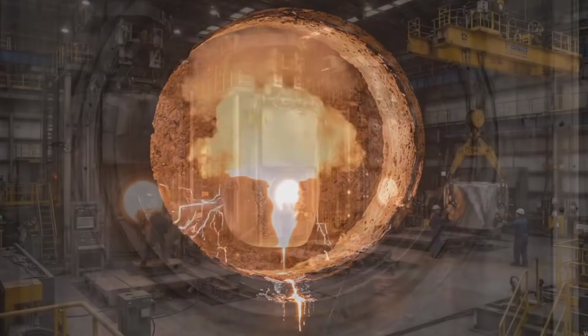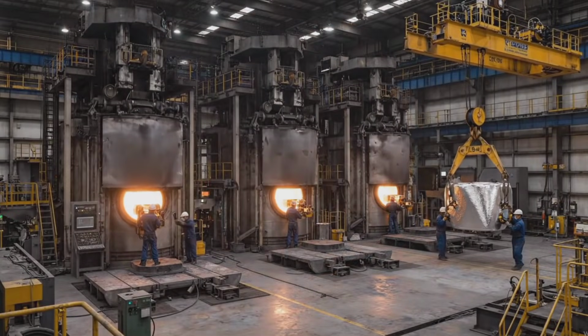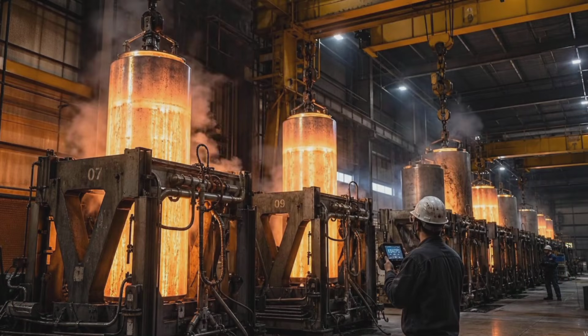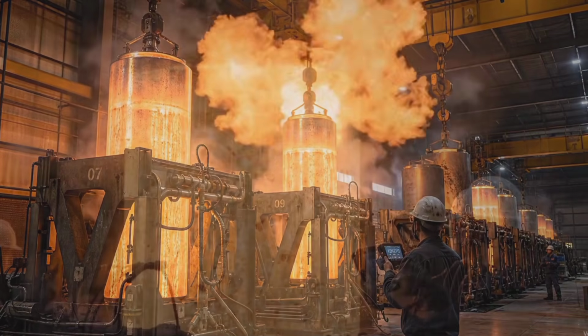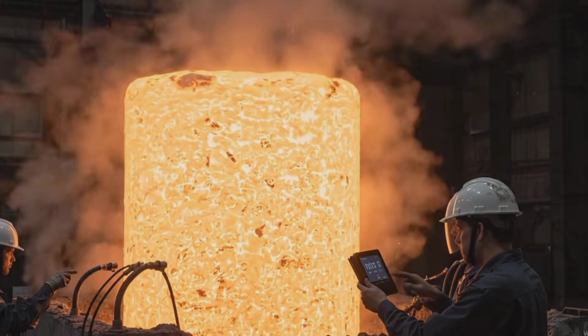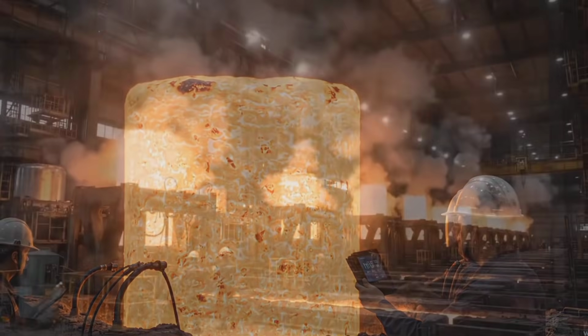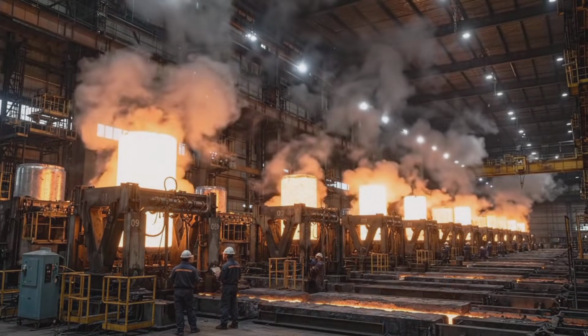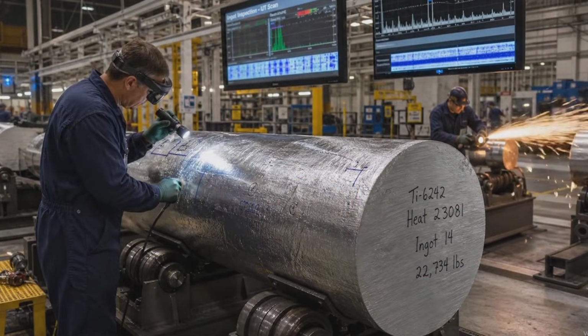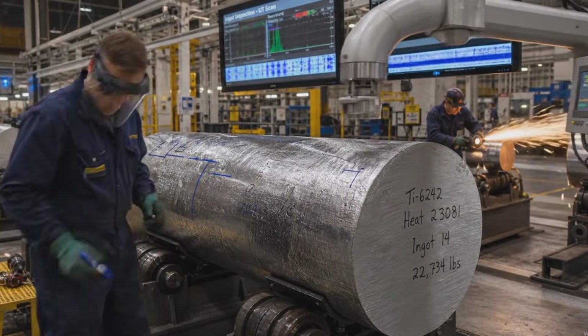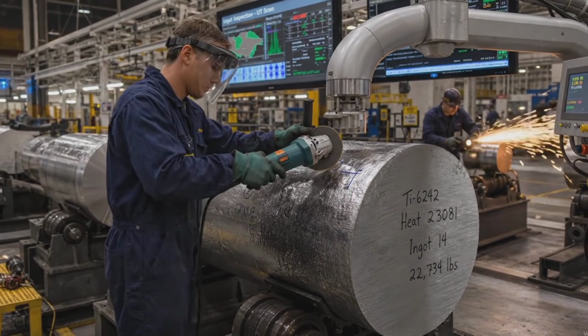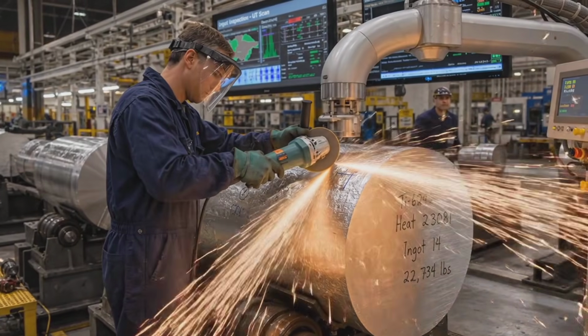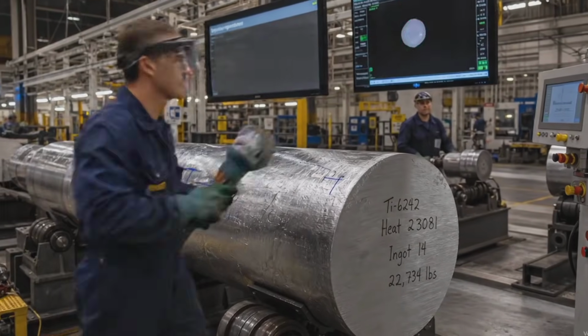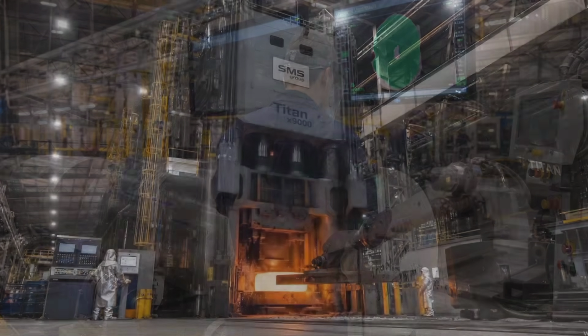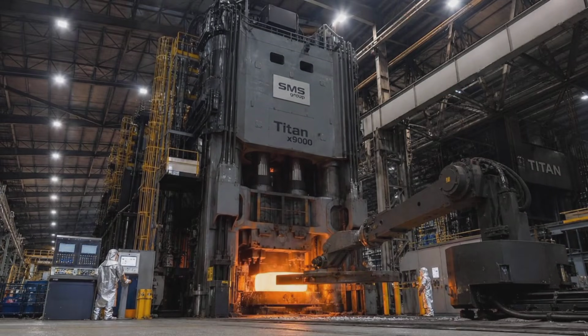Inside vacuum arc remelting furnaces, tens of thousands of amps pass through the electrode. The electric arc burns with blinding intensity. Metal melts, drips, and solidifies into a solid ingot inside a water-cooled copper crucible. This process repeats 3 times, eliminating every trace of impurity from the metal structure. The final ingot is a massive silver cylinder, weighing up to 10 tons.